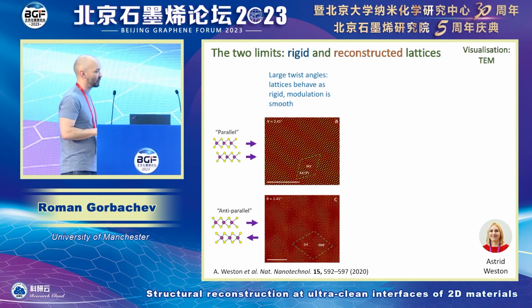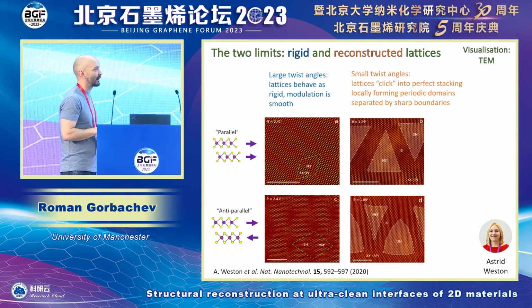And what I'm going to show you briefly is that these are producing completely different quantum systems. So this is freedom that is given to us by twistronics in terms of exploration of really quantum physics and low temperature physics. And so if we twist them at very high angle, for example, 3 degrees or 2 degrees, you don't really see much happening. So you have this periodic modulation of the atomic registry. But if you go for smaller angles, you start seeing these commensurate domains that are basically a perfect bilayer.